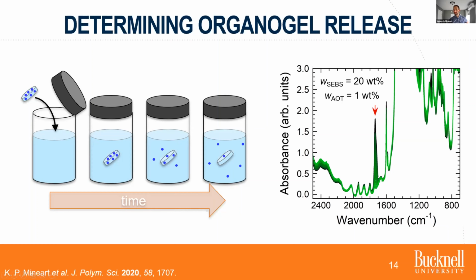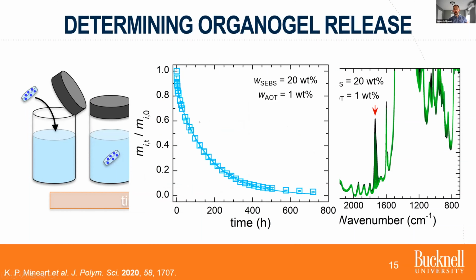Here, this is from black to light green, indicating the progression in time. And as you can see, the height goes down because the AOT is releasing from the gels. And therefore, we're seeing this diffusion that I was just talking about. This is some example data for a triblock copolymer concentration of 20 weight percent initially, and an AOT concentration of 1 weight percent initially. And then we can take these and basically plot up a release curve with time.